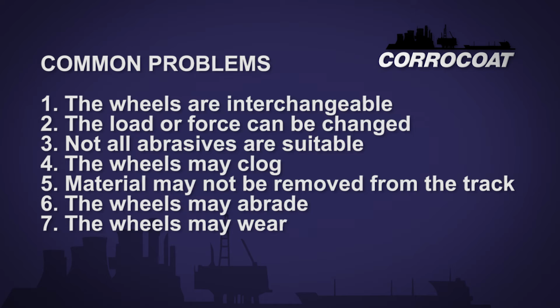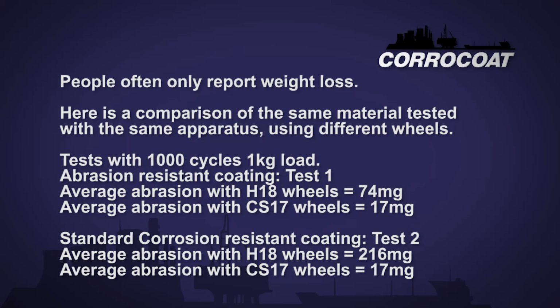As a result of the above issues, when comparing results, great care has to be taken to compare like with like. What should be reported is not only the weight loss, but the type of wheel, load, and the number of revolutions or cycles. Here is a comparison using two different wheel types on the same material.